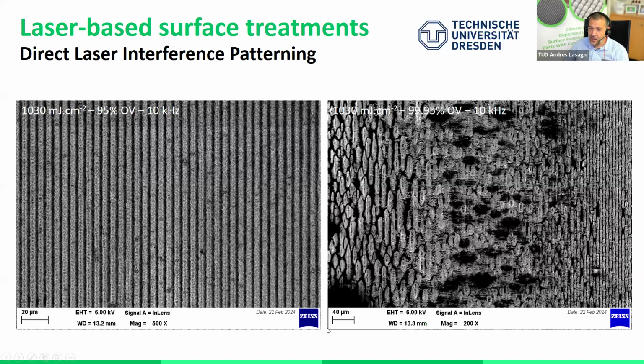And where is this coming from? In particular, when we are using very high overlap, for example, here 99.95%, we start to destroy our periodic structure. We have a heat accumulation. We are bringing a lot of defects. This is, of course, something that we don't want to have. And in the case of overlaps, let's say up to 95%, maybe a little more, we can get very perfect periodic lines in this case. And these are the structures that at the end we need to create a spatial surface function.